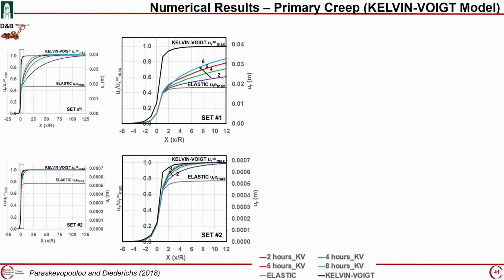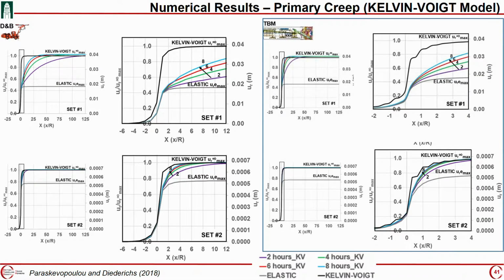So it depends on the viscoelastic parameters that we estimated in the lab, and all of these things that I was discussing previously. And again, for the TBM, you can see the difference between the tunnel lengths. On the TBM analysis, you can see that it converges closer to the tunnel face because the tunnel advancement is one length. So 1 meter, 8 hours, 1 meter, 8 hours. At the end, you will get your maximum tunnel wall displacement closer to the face, but in a longer period of time, if you understand my thinking.